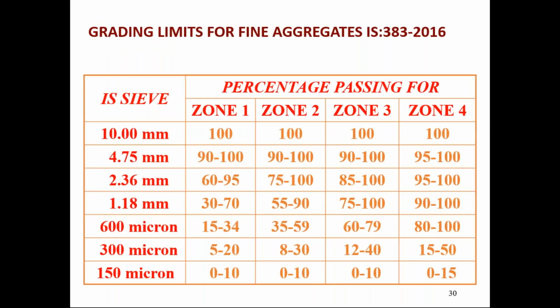If you look at the requirements of gradation of aggregates, we use this particular requirement as per IS 383. That is starting from 4.75 mm. Of course, there is a 10 mm sieve also shown here. 4.75 mm downwards: 2.36 mm, 1.18 mm, 600 micron, 300 micron, and 150 micron. There are four zones of sand: zone 1, zone 2, zone 3, and zone 4. For each zone, there is a percentage passing requirement specified in IS 383.